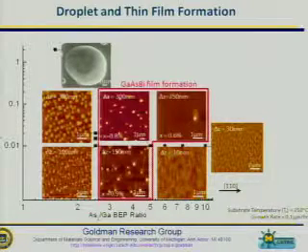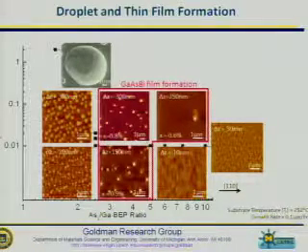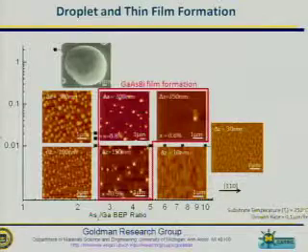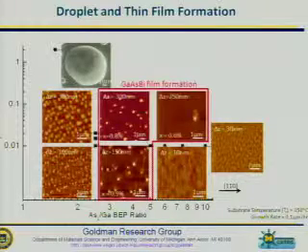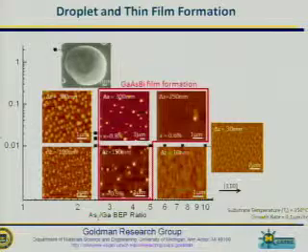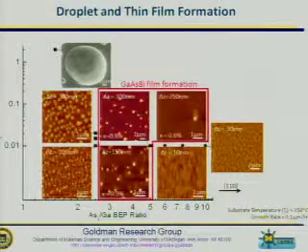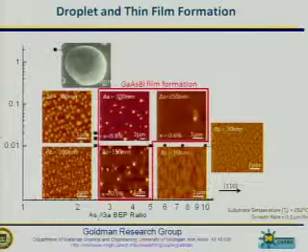You'll also see that we've observed gallium arsenide bismuth film formation at only a certain range of arsenic to gallium BEP ratio, between 5 and 6. You'll also note that each of the AFM images has a different delta Z scale. This shows us that our features are of varying height scales, and gives us an idea of the order of magnitude of the height of the features.